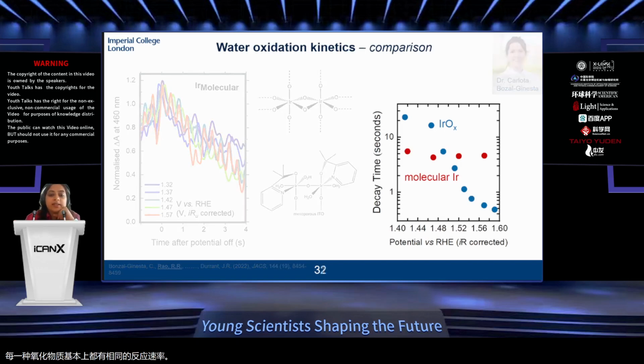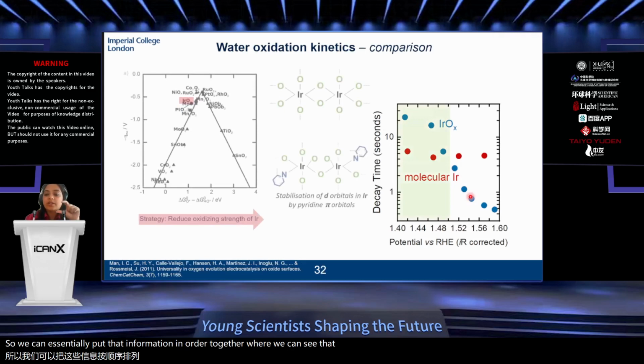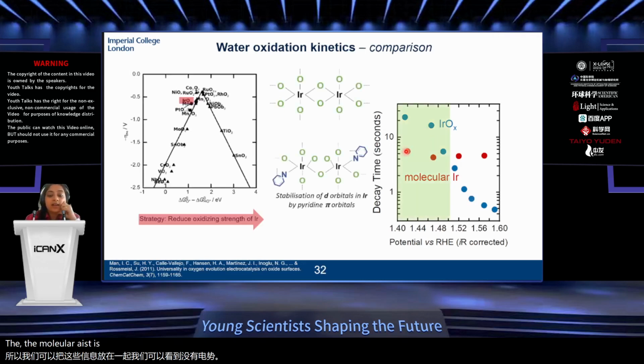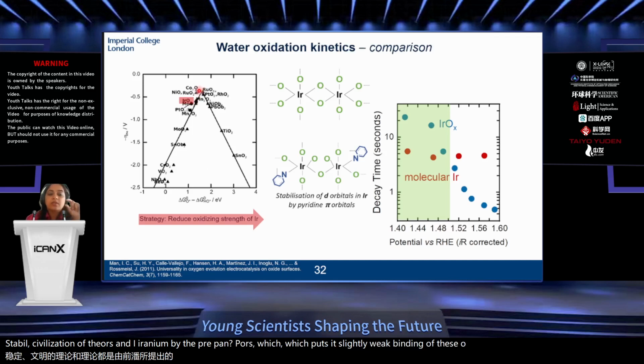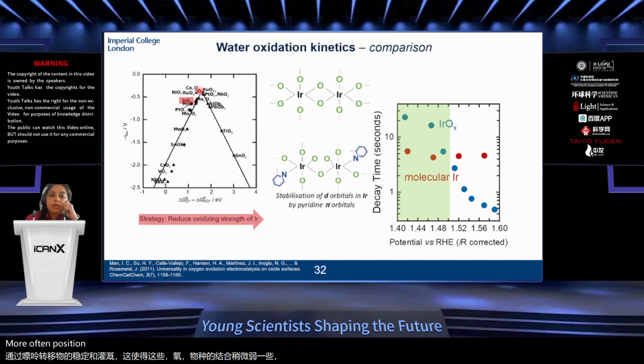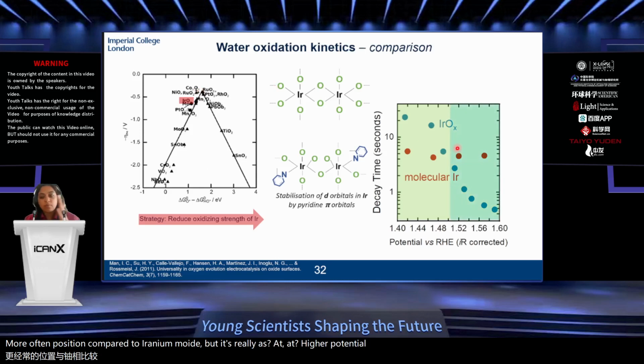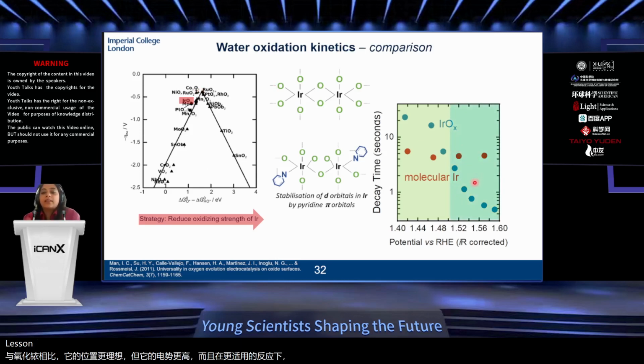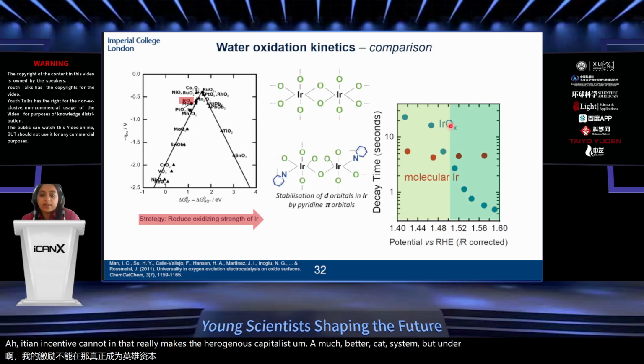So we can put that information all together, where we can see that at low potentials, the molecular catalyst in fact has faster kinetics, and that's because of this stabilization of the d orbitals in iridium by the pyridine pi orbitals, which results in slightly weaker binding of these oxo species and a more optimal position compared to iridium oxide. But at higher potentials and under more applicable reaction conditions, while this heterogeneous iridium oxide can access these cooperative interactions, the molecular iridium centers cannot, and that really makes the heterogeneous catalyst a much better catalyst under these conditions.